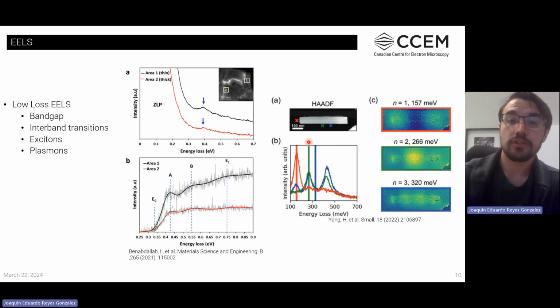By locating our small probe at different positions, it is possible to extract different EELS spectra coming from each of these positions. So the red one corresponds to the edge, to the face of the nanorod, and then the green and blue ones are located at different positions in the edges.